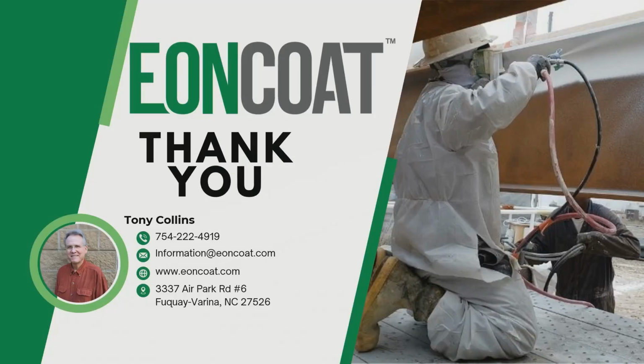Excellent question. The question was, does the coating shield CP, cathodic protection? You can use cathodic protection in conjunction with this technology. We've tested it multiple times. The thing that makes coatings fail due to cathodic protection is something I referred to earlier. If the voltage gets significant enough, you form a lot of sodium hydroxide.